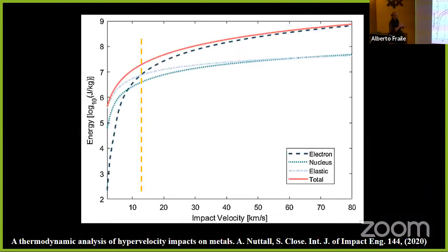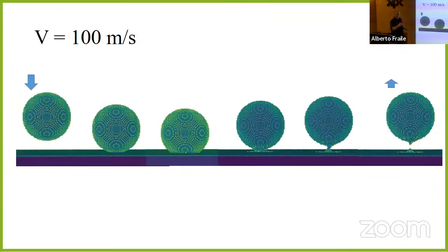And then up to what velocity can we really go with classical molecular dynamics? In this paper, they analyze the contributions and the thermodynamics of the hypervelocity impacts in different metals. So for tungsten, in this graph, this is the total energy, the red one, and then this one, the light blue, is the elastic contribution in impact, and then the other one is the electronic, this one. So above 12 kilometers, more or less, the electronic contribution is higher than the elastic. So we cannot ignore the electronic excitation that you have in the target at very high velocities. So that's why we went up to 12 kilometers, and even less will be safer.